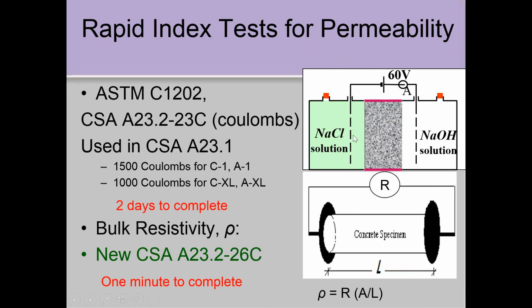So the top test is the 23C. You take a 2-inch or 50 millimeter thick disc of a cylinder, you put it between two cells with salt solution or hydroxide solution in, apply a voltage and measure the electric current that flows through the concrete. You measure that over 6 hours, you multiply the current times time, and you get coulombs. That's the test people have been using for the last while. And so it's a fairly rapid test, but it takes a day to set it up to vacuum saturate.